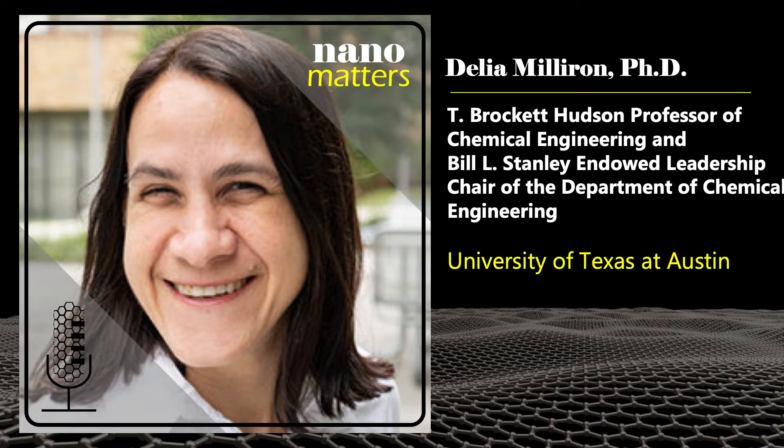So how does nanotechnology play a role in these windows? We make our coatings from nanocrystals — very small pieces of the active smart window materials — and their small size really fundamentally changes the way they interact with sunlight. That gives us more control over the selectivity of the window with respect to visible light and to heating. For example, using nanocrystals unlocks what we call a cool mode of the window, where it still transmits most of the visible light for interior spaces but blocks as much of the heat as possible. The nanostructuring also speeds up the switching, so making them small allows them to more rapidly change their tint, which expands potential applications to things like cars or trains.